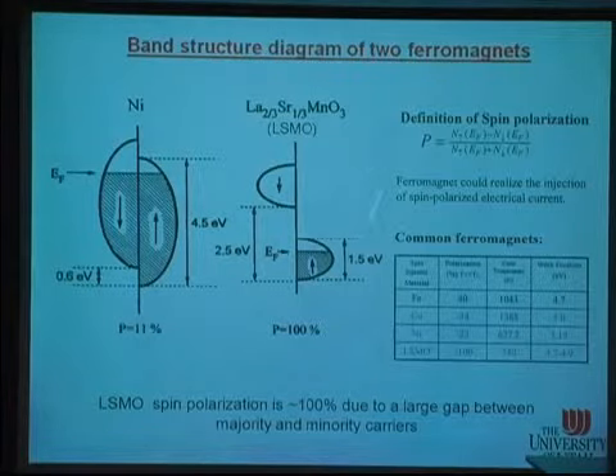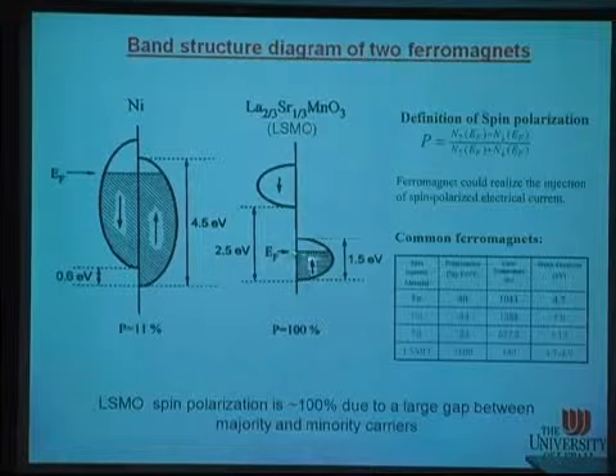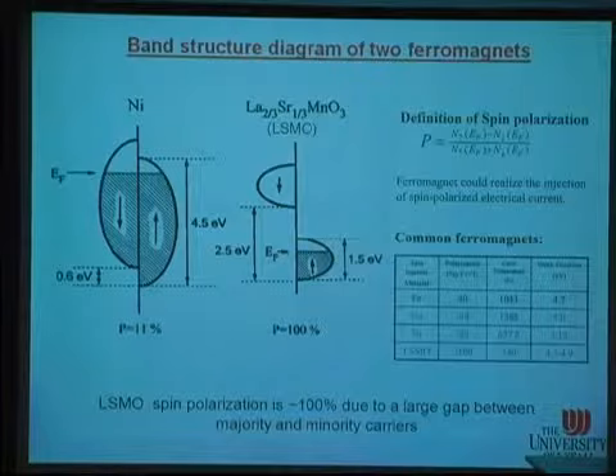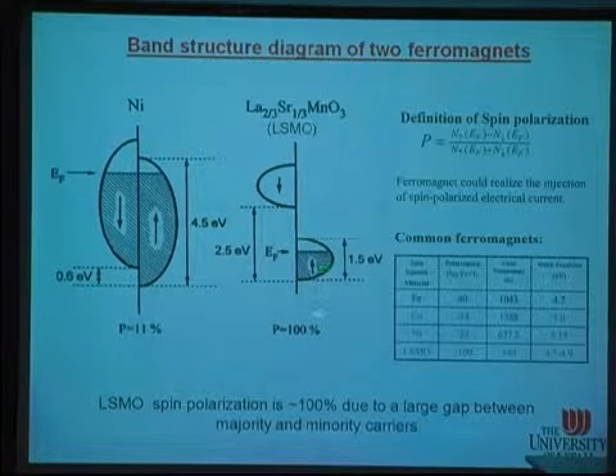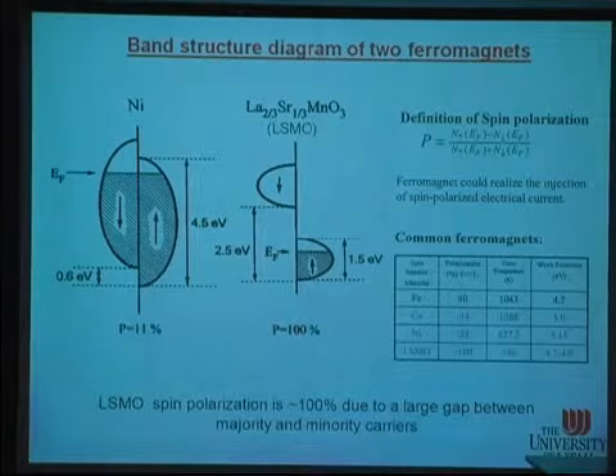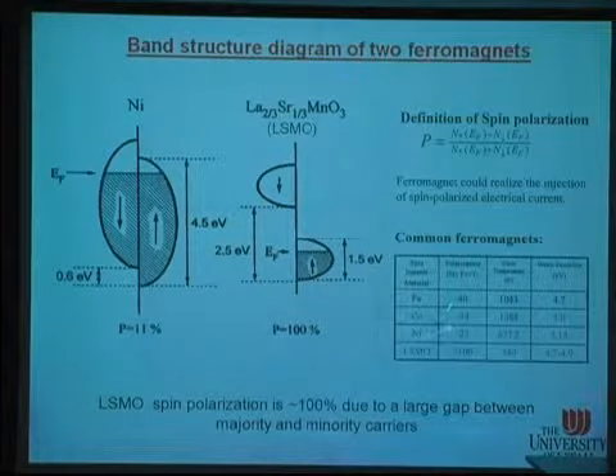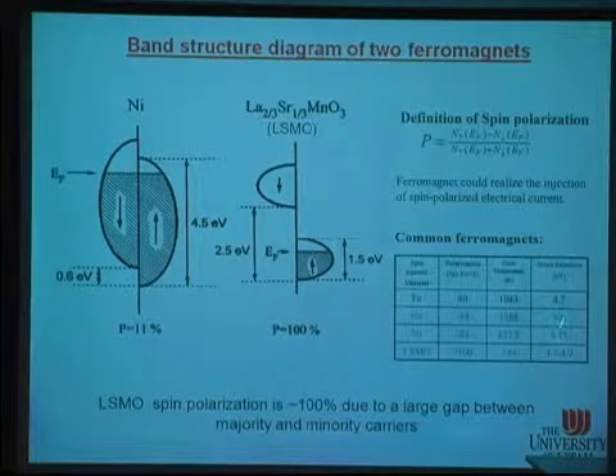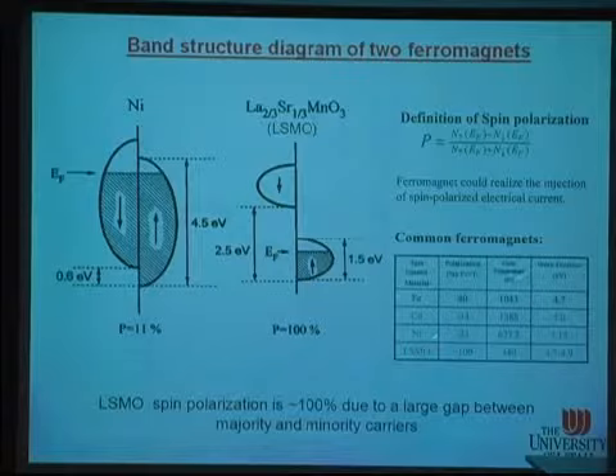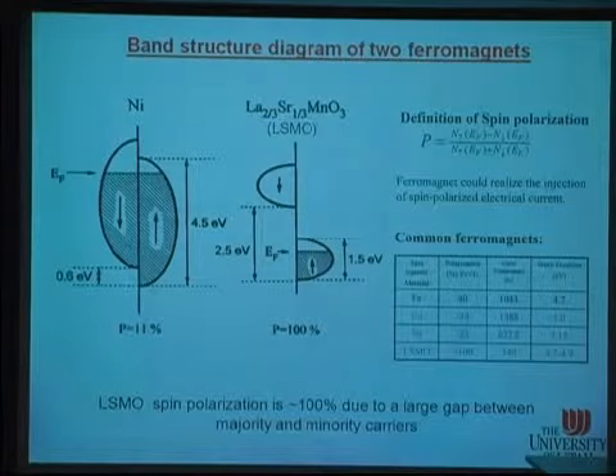But if you consider the LSMO, the Fermi energy lies just in one spin electron band, which means the spin polarization here is 100%. And in this table, I give you some idea about the spin polarization of iron and other materials, and also the Curie temperature and the work function. You can see the work function here is quite high. Those materials are good only for hole injectors, not for electron injectors.